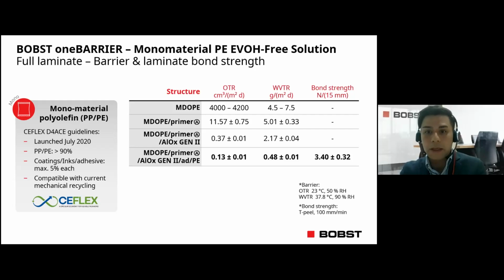plus MDO capability. The One Barrier primer provides exceptional oxygen barrier properties. When we combine this with our AlOx Generation 2 process, we further improve the oxygen and water barrier level. And when viewing the complete laminate with a selected barrier adhesive, we are able to provide a solution that enters the domain of metallized polyester film replacement with a laminate bond strength that passes the market requirement of 2 to 3 newtons per 15 millimeters. We were able to achieve similar barrier results with AluBond as well.